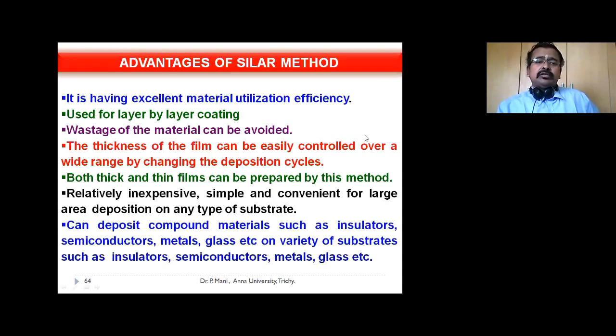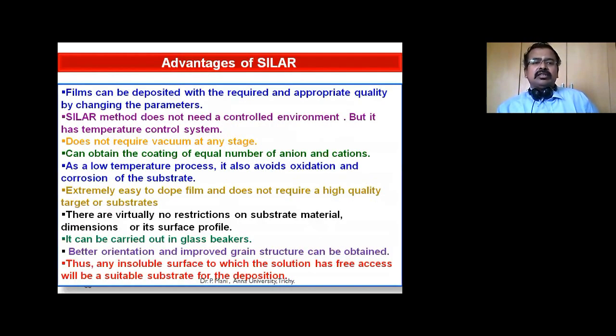Okay, advantages. So many advantages are there. Excellent material utilization efficiency and layer by layer coating. Wastage of material is reduced here, and the thickness of the material film can be controlled easily. Thick and thin films can be prepared by this method inexpensively, simply, and conveniently for large area deposition on any type of substrate. And we can deposit compound materials on a variety of substrates such as insulators, semiconductors, metals, glass, etc. And we can coat the films with required and appropriate quality by changing the parameters.